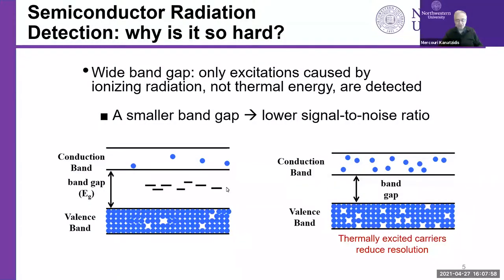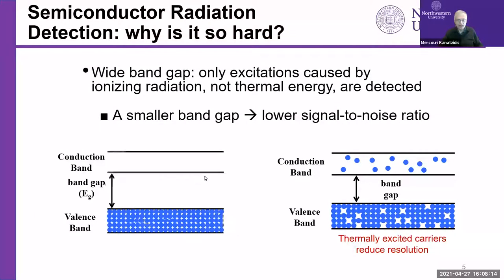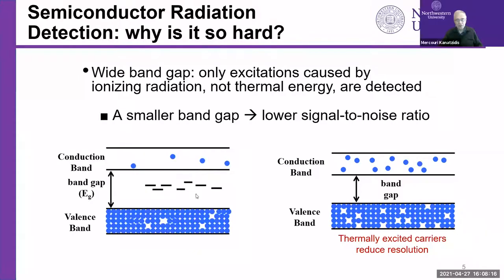So you want a big enough band gap, and then you also want the gap not to have too many traps from impurities, from imperfections, defects that can capture the carriers that are generated when you absorb the radiation. And so you need to have more carriers than traps, basically.